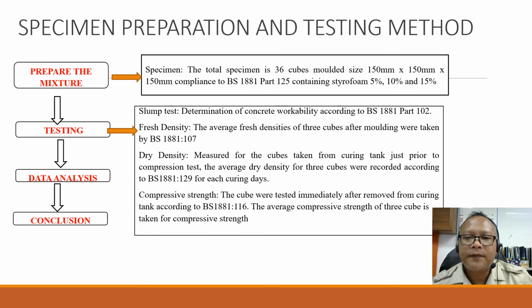For testing, firstly is the slump test, which is determination of concrete workability according to BS 1881 part 102. For the fresh density, the average fresh density of 3 cubes is taken by BS 1881 part 107. Meanwhile, dry density is measured for cubes taken from the curing tank prior to compressive test, recorded according to BS 1881 part 129 for each curing day. For the compressive strength, the cubes were tested according to BS 1881 part 116. The average compressive strength of 3 cubes is taken.